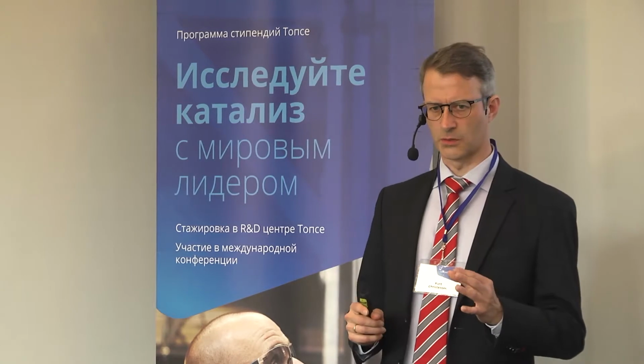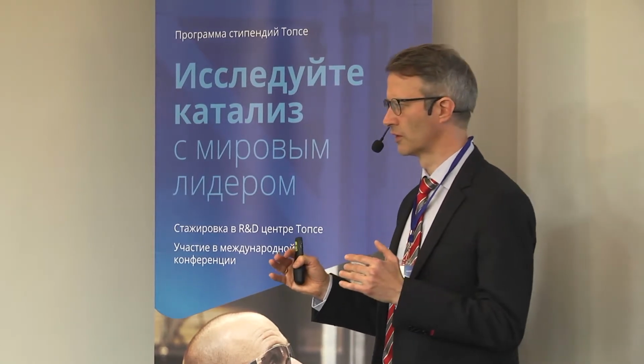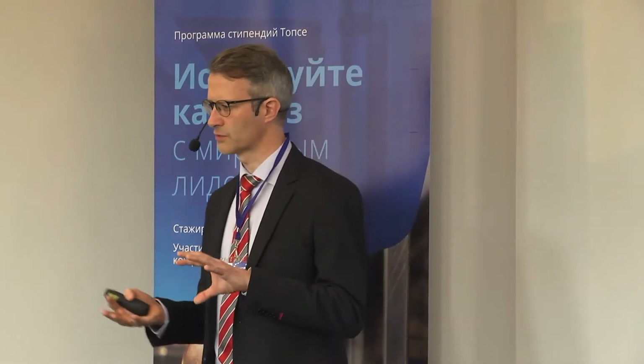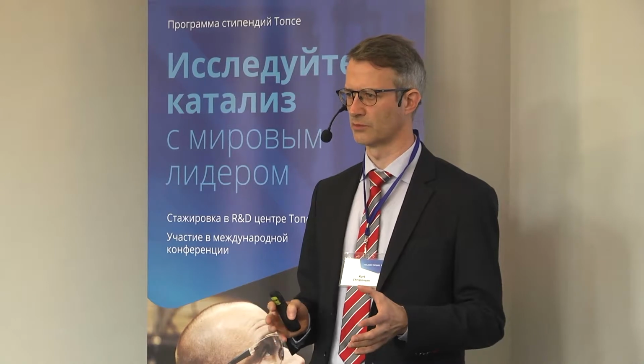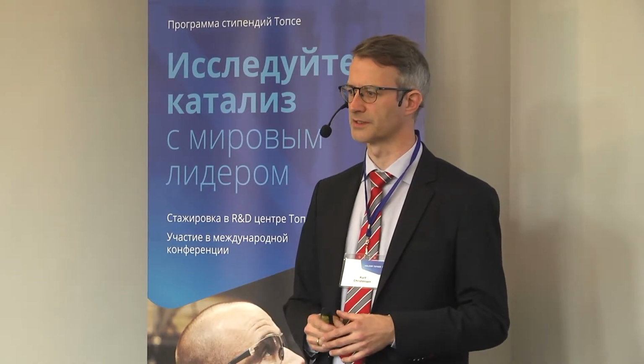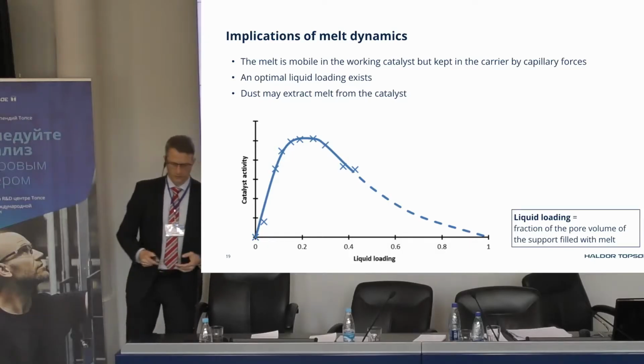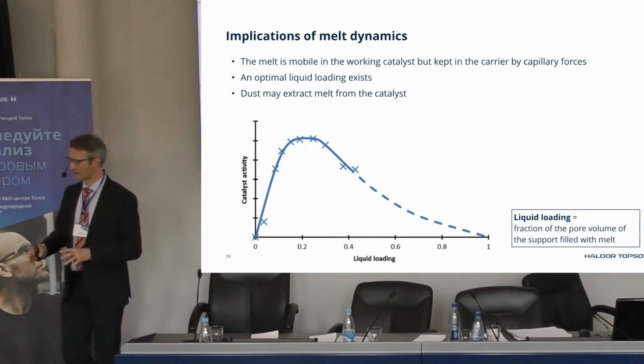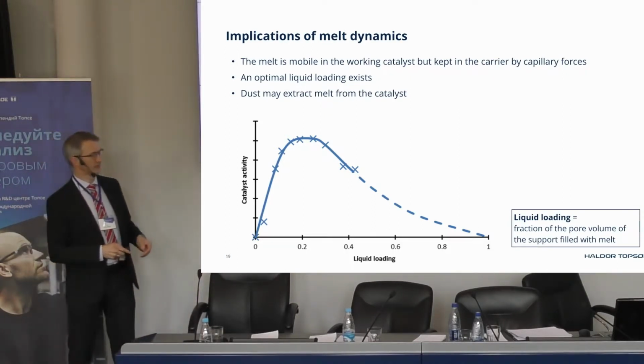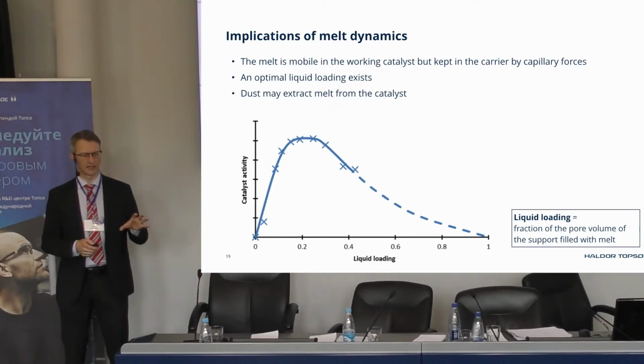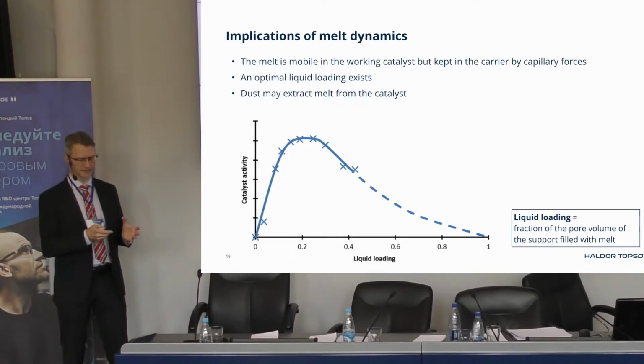From these studies, we can learn about the equilibrium distribution, and in this way we can tune the carrier systems we work with and improve the catalyst. We can also learn about the melt migration rates, which will be very dependent on especially temperature. If we zoom out to the lab scale, industrial scale again, it has some implications that the melt is mobile. This is different from the heterogeneous catalysts.